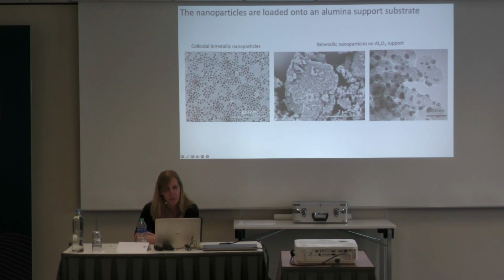In this case, with the acetylene hydrogenation, the silver palladium on the alumina support seems to minimize sintering. The catalyst nanoparticles, at least before and after catalysis, seem pretty much the same, but I think there's a big opportunity to look at these in the TEM and follow how single atom alloys might be migrating around the surface. We haven't done that yet, but at least it doesn't seem like there's a change in activity with time for these particular catalysts.